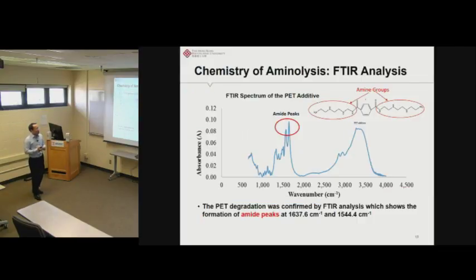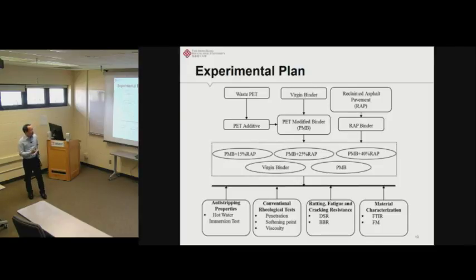To verify whether our aminolysis process is successful, we conducted some chemical analysis through FTIR, Fourier transform infrared analysis. And here is the spectrum of our additive. In the spectrum, we can clearly see these two peaks, which belong to the amine groups. Because we can successfully identify these peaks, that verified our aminolysis process is successful. We did introduce the amine groups into the additive. So after such preliminary investigation, we decided to do further investigation. So we made such an experimental program to run more tests on the binders which have been added the additives, to see how this additive is going to change or affect the binder's properties.